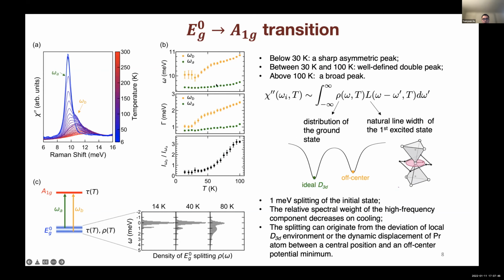In figure B, we show the temperature dependence of the positions, line widths, and the relative spectral weight ratio. Based on this analysis, we conclude the ground state doublet is remarkably split by about 1 milli-electron volt above 30 Kelvin. And the relative spectral weight of the high frequency component omega B decreases on cooling, and the temperature dependence is reversed to the thermal population.